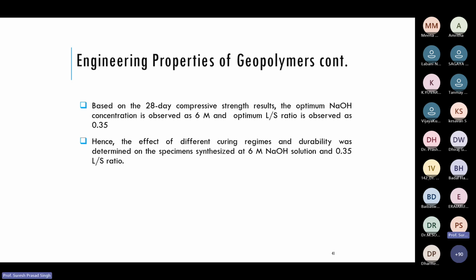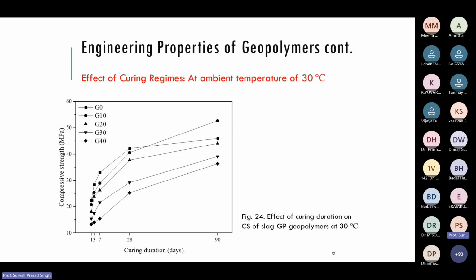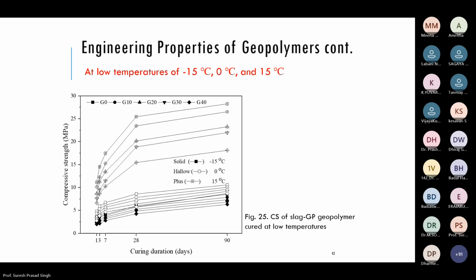But if you don't use this glass powder, this optimum molarity of alkaline will be 8. So you are saving 2 molar sodium hydroxide if you use the glass powder, because glass has sodium in it. So this is about the ambient curing 30 degrees, and this is the strength gain with the curing period of 90 days. Yes. I have only 20 minutes, okay.